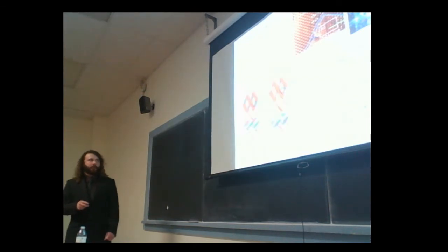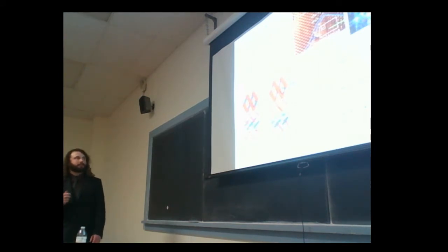The reason why they're decreasing as you turn clockwise or counterclockwise is that the CDW vectors actually change direction as you go into the material. So here it's going to be red, green, blue, and here it's going to be red, blue, green. And that's the left-handed and the right-handed domains.